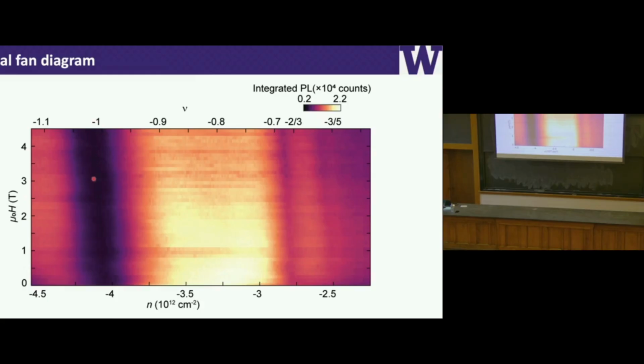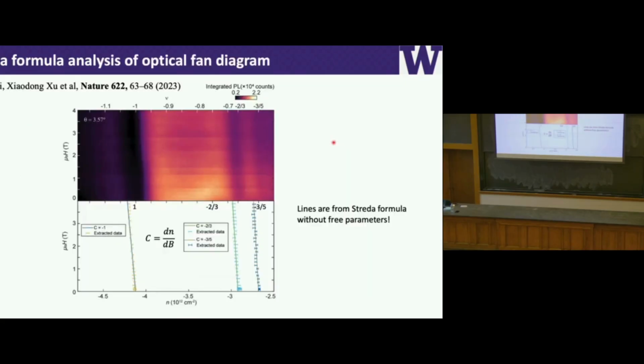First of all, the integer feature at filling -1, right? You see the line is actually tilted, and it has fractional fillings -2/3 and -3/5. So we can extract the carrier densities corresponding to these dips and plot them as a function of magnetic field. Then we can overlay the Streda slopes on top of these extracted densities. This gives us the assignment of Chern numbers, right?